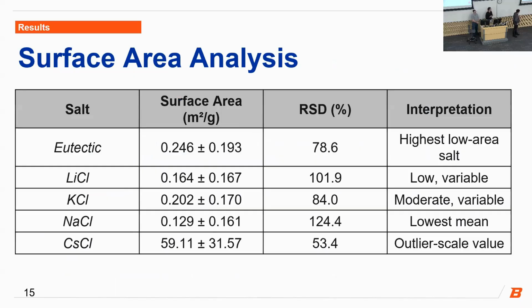Now, moving into our results data tables, this first one is the surface area analysis. As you can see from our surface area values, most of them hover between 0.13 to 0.25 meters squared per gram. These are relatively believable values in accordance with literature. However, it's important to note that there's not one set in stone value because different salt manufacturers have different purities and salt specifications. The RSD, or relative standard deviation, is useful here because the absolute means of these samples are very small, which means that very small measurement differences appear large proportionally.